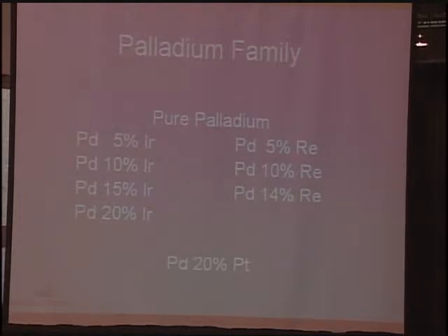For the palladium families, we looked at what we know best, and we had a history of the platinum iridium, and we went ahead and just swapped out platinum for palladium, and we now have a family of palladium alloys with increasing content of iridium, and these materials are already available in the marketplace. We also expanded to palladium rhenium alloys, where the rhenium is added for strength. We also have a palladium 20% platinum alloy that does offer advantages, once again, where you've got 80% palladium, so you've got a lower density material.